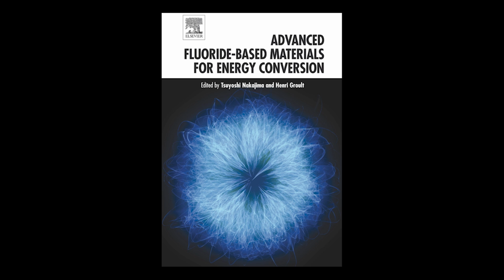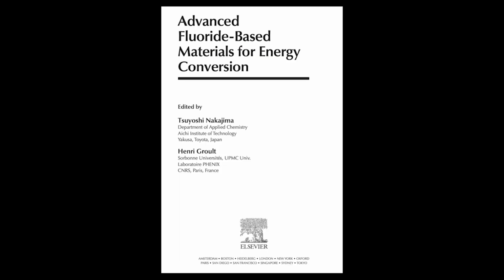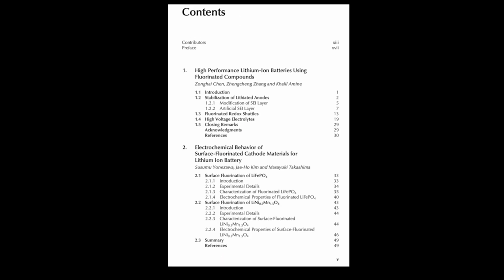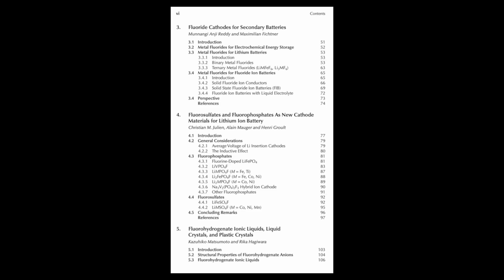Meaning some fluorine atoms are interacting with lithium ions, sort of ionically bonded, and others are directly bonded to the transition metals like manganese and nickel. It even seems the fluorine diffuses a little bit into the particles, not just sitting right on top. Fascinating. It's like giving the battery material a fluorinated suit of armor. That's a good way to put it, yeah.